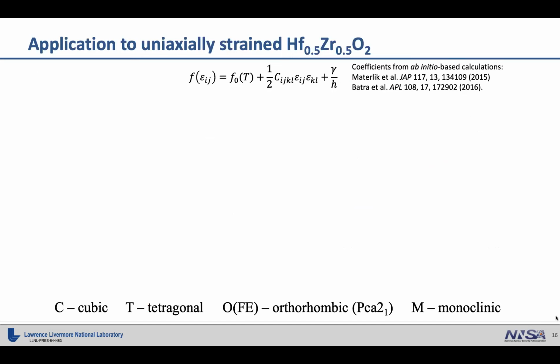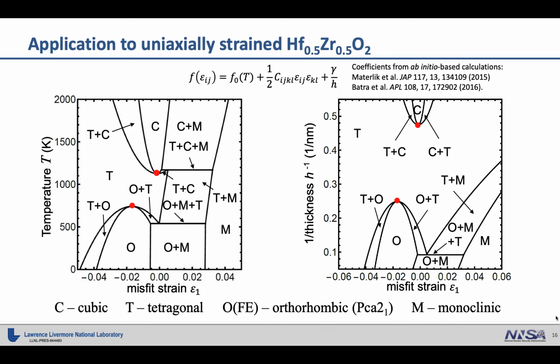There are a lot of details here, and I will skip those. To show the most interesting work, I think recently we have had a strong interest in hafnium zirconate. And we found that with a very simple model, we can predict the phase diagram of hafnium zirconate. Again, we're starting with a very simple model, only considering the bulk free energy, the total free energy at 0 K and as a function of temperature, and also the elastic energy term. In addition, there's a surface energy term, which scales inversely with the film thickness. All of the parameters can be found from ab initio calculations in the literature. With this simple model and the common tangent construction, we can obtain the temperature-misfit strain phase diagram for hafnium zirconate systems. As well, we can obtain the thickness versus misfit strain phase diagrams.